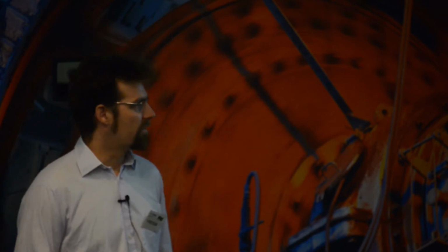In the tails leach, uranium and copper are solubilized, and they proceed to solution purification through two stages of solvent extraction. The first is cation exchange to recover the copper, and then that copper is turned into copper metal by electrowinning. And then uranium's recovered by anion exchange solvent extraction. It's stripped from the organic, precipitated, and then calcined to uranium oxide product.